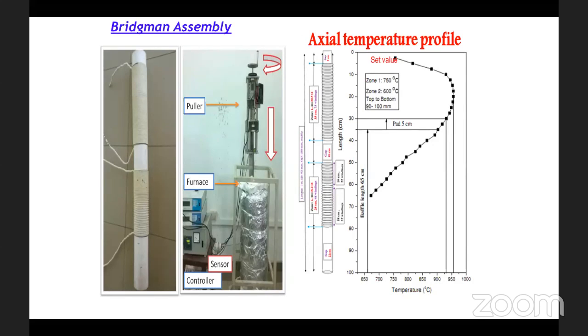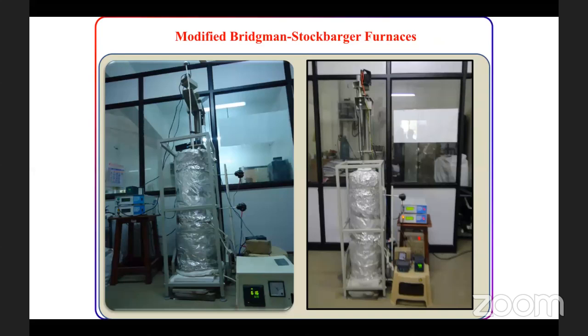In this technique, you have a top zone. As I told earlier, you have the top zone and bottom zone. Based on the material, you can set the temperature. Let's say for my material, I set 750 degrees for the higher end, and zone 1 and zone 2 at 600 degrees. When you pull down the crucible, it starts to nucleate at the bottom of the crucible, then it will grow big size crystals.